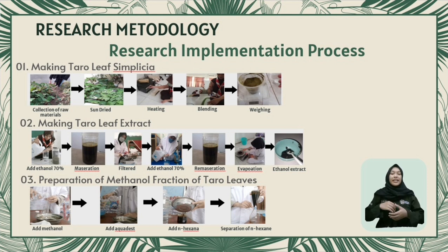The second is making taro leaf extract, include add ethanol 70%, then maceration for 5 days, then filter the first filter, then add ethanol 70%, then remaceration, after that evaporation, and so that the ethanol extract is obtained. The last is preparation of methanol fraction, include add methanol, aqueous, and hexane, and separation of N-hexane.